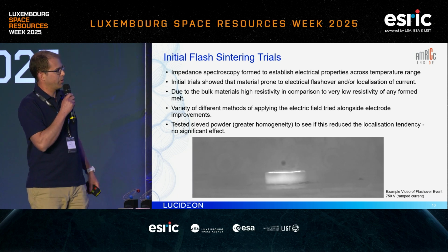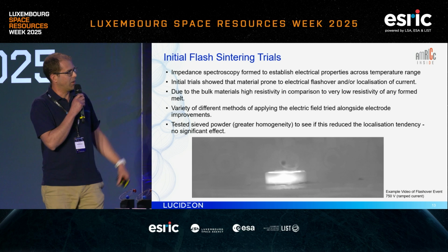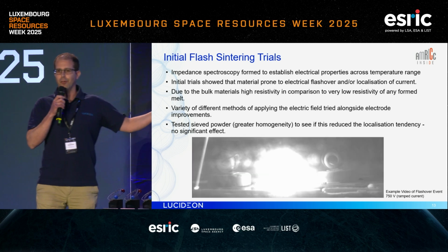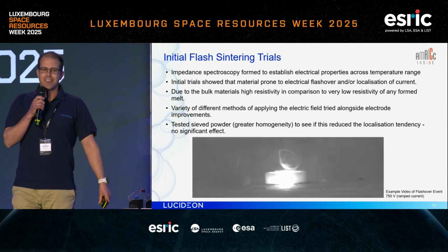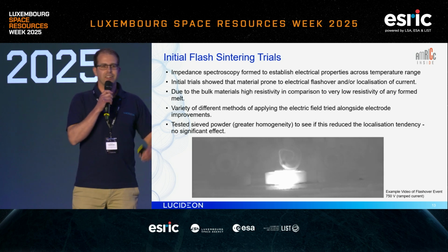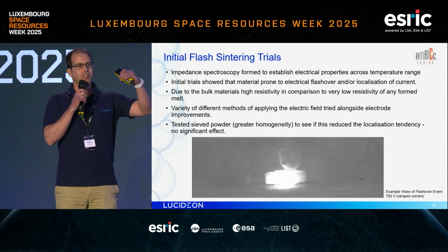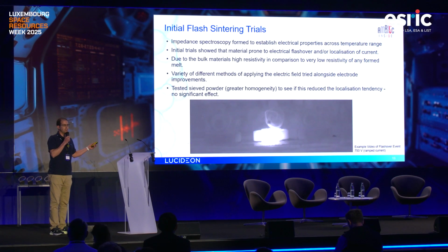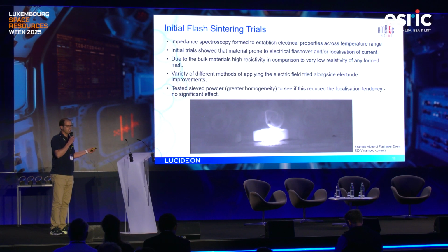So if we play this video, we start to apply the electric field, we're getting some nice, and then all of a sudden we get the fireworks. So what we're seeing here is we've ignited a melt and a localization point, and there's some thermal runaway there. So we're overcooking the middle and we're not touching the sides, essentially. And that's quite common, but it does show that the material's very receptive to electric fields under these conditions.